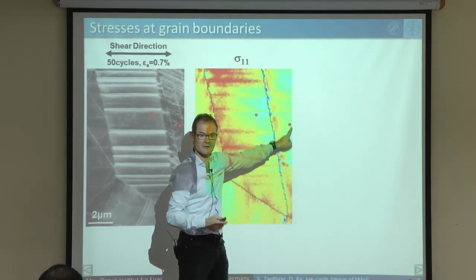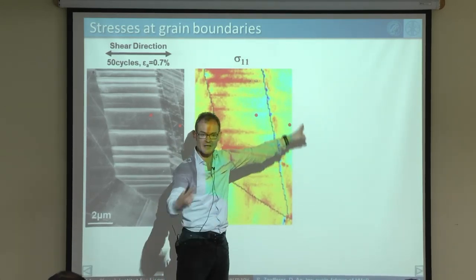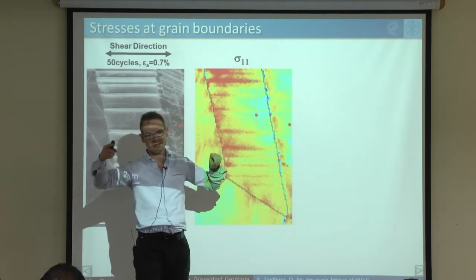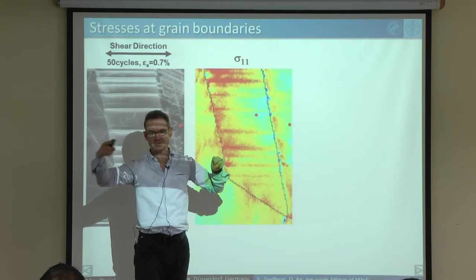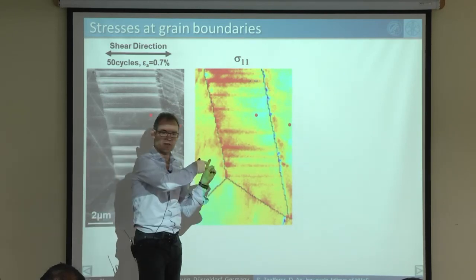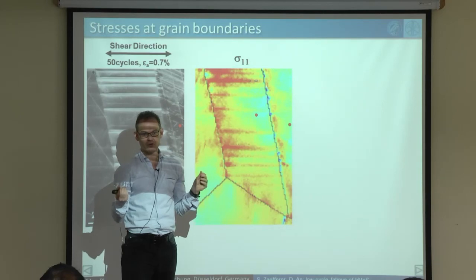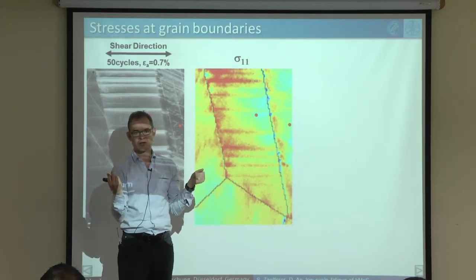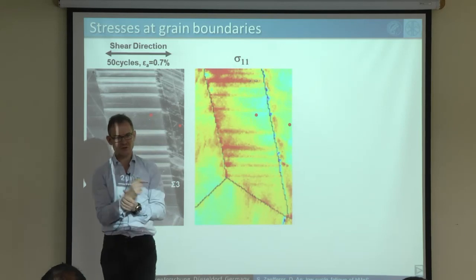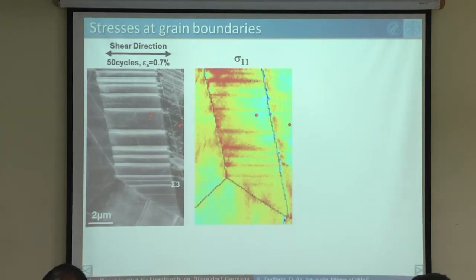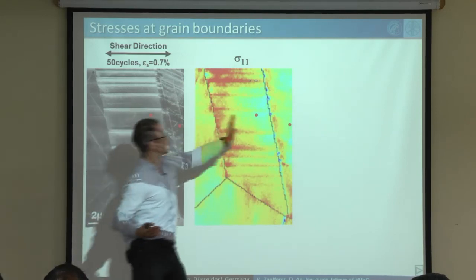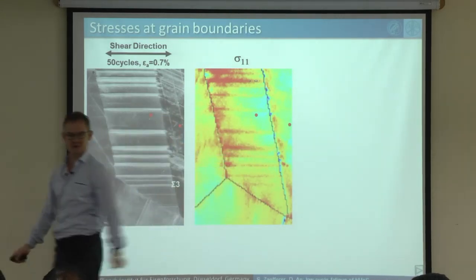The other side of the grain would have been measured with respect to another reference point in another grain. And if you have a phase boundary, again, you must have as a reference point a point in the second phase and in the first phase. Across that, there is no possibility because you don't have an absolute measure. You have only a relative measure of residual stresses, and it would be nice to have an absolute measure. That fails because we are not accurate enough in finding the pattern center of the EBSD pattern. So currently you can go to a grain boundary, but not across it, with these measurements.